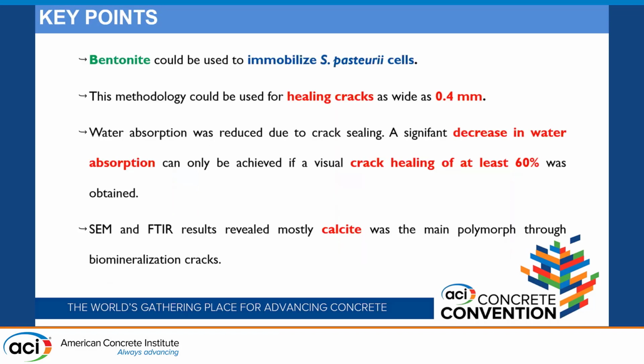To sum up, bentonite could be used to immobilize S. pasteurii cells, and this methodology could be used for healing cracks as wide as 0.4 millimeter. Water absorption was reduced due to the crack sealing, and when we compare all our studies, we can say that a significant decrease in water absorption can only be achieved if a visual crack healing of at least 60% was obtained. Moreover, our SEM and FTIR results show that mostly calcite was the main polymorph in the biomineralization cracks.